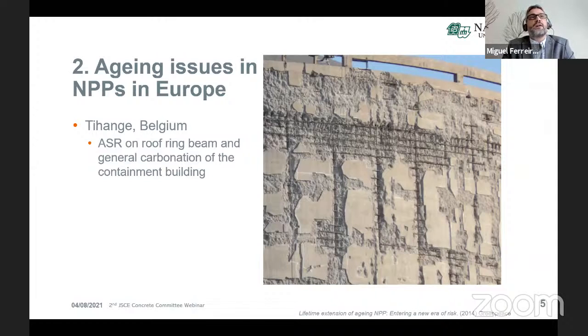And in addition to that, on the upper part of the containment structure, and this you can see in the photograph, there's been extensive carbonation of the reinforcement due to poor concrete cover, and of course corrosion and spalling of the concrete cover. So of all the aging deterioration mechanisms that affect concrete structures that I can think of, there's one that's unique to nuclear power plants, and that is the deterioration that is induced by neutron and gamma radiation. And this Professor Maruyama will talk about a little bit later. Otherwise, the concrete structures of nuclear power plants are subject to the same aging mechanisms: chloride-induced corrosion, ASR, sulfate attack, etc.